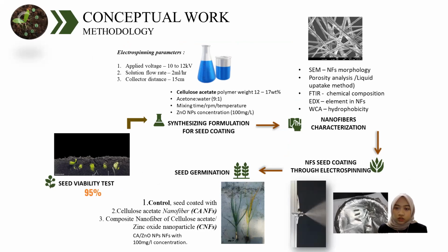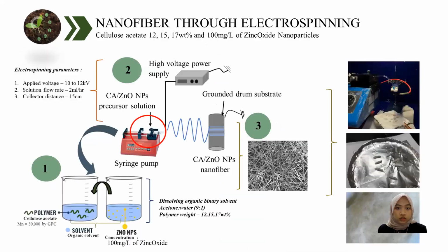Using the instruments of SEM for the morphology, we're going to study the porosity and liquid uptake, FTIR, EDX, and water contact angles. And then we're going to proceed with the seed coating through the electrospinning process and conduct the seed germination to study the germination rate between the control, cellulose acetate nanofiber alone, and cellulose acetate with the inclusion of zinc oxide nanoparticles at 100 mg per liter concentration.